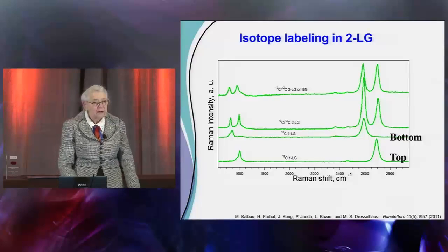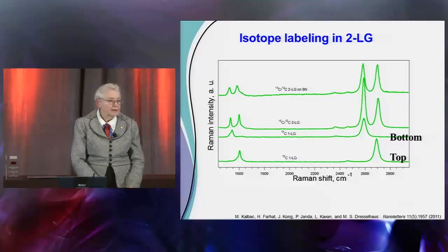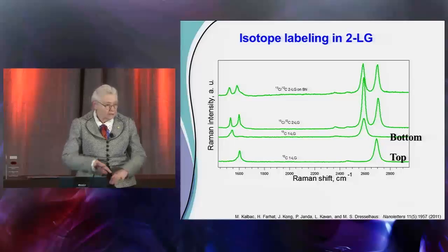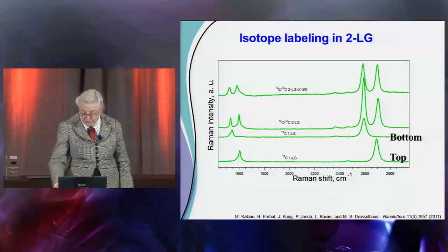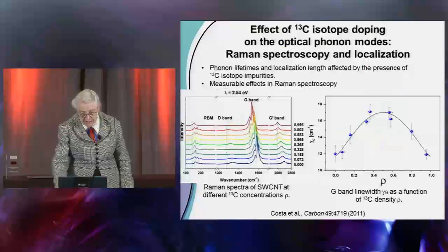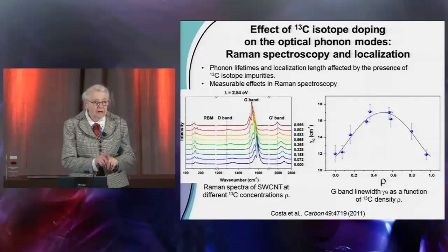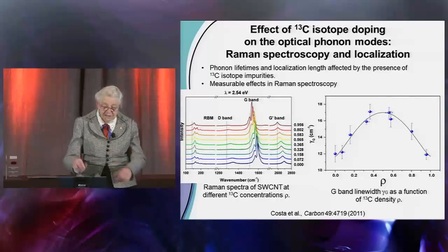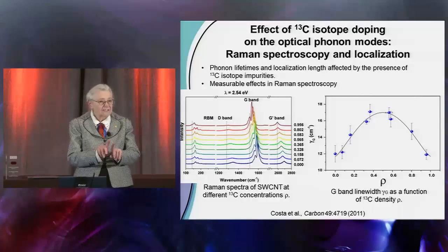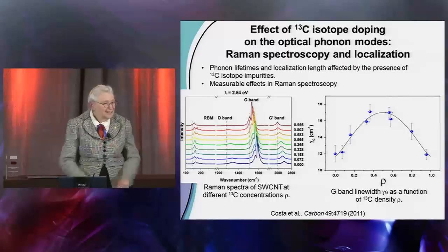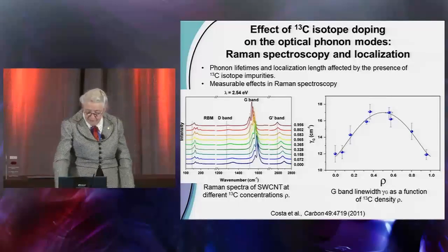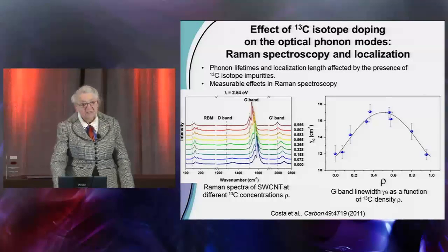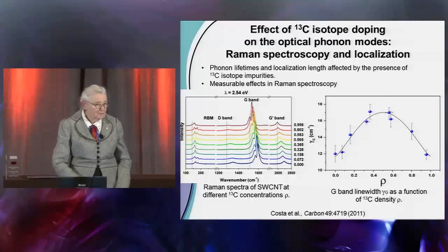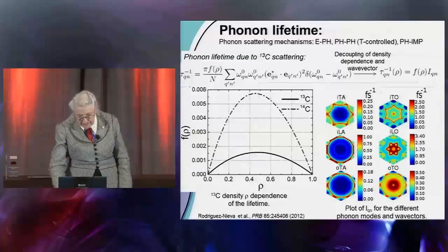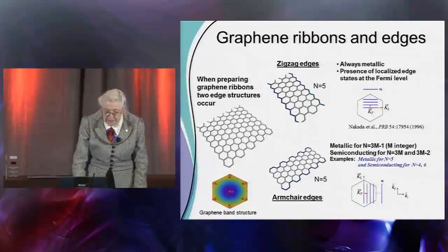So you can tell what's happening in surface effects. You can have environmental effects because you can separate all of that. If you have two layers, you can know which is the top and the bottom. Put C12, C13. So that sort of thing can be done. And you could also look at localization effects. This is something: what happens if you have a C12 next to a C13? Does that make a big difference whether you have it or not? It's not going to change the electronic properties very much, but the phonons will change quite a bit. And so you can study lifetimes of these kinds of states.